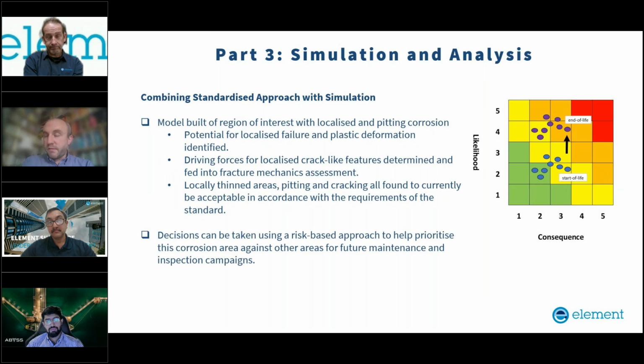And so we were able in this case to demonstrate that the pitting corrosion, the localized corrosion, and the crack-like features that were found were not actually immediately threatening the integrity of the pipework. We were able to demonstrate that, given an assumption of a level of damage propagation over time, those areas of damage would start to become a threat over time.